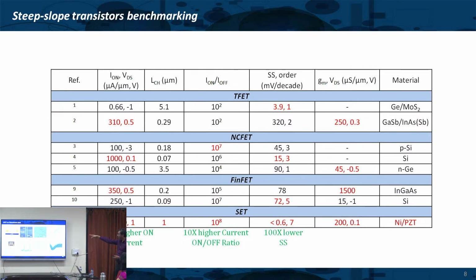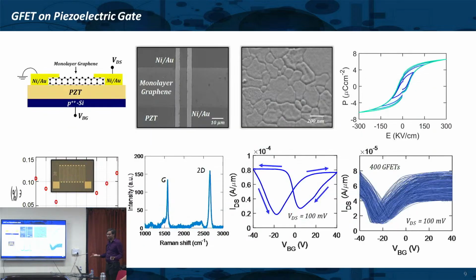So you can put graphene as a channel, because at the end of the day, remember, we also need a GM. Metals will not give you GM, there is no gain, correct, because there is no change in current as a function of gate voltage. So I have to bring in a channel material that will give me the highest mobility, highest GM. And graphene we could not use for normal transistors, but now I can, because on state it will be graphene, off state is just an insulator, which I could not get with graphene because it did not have a band gap.